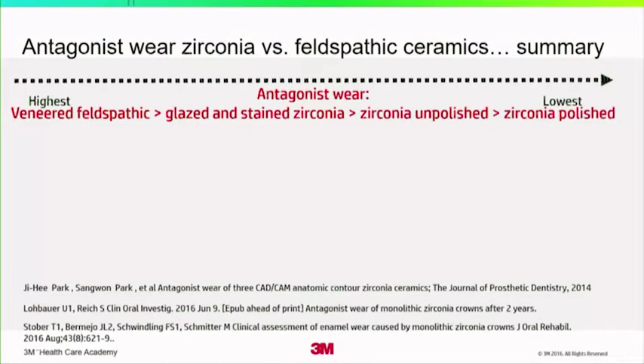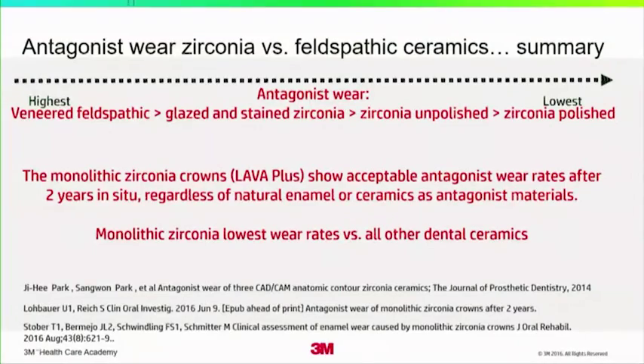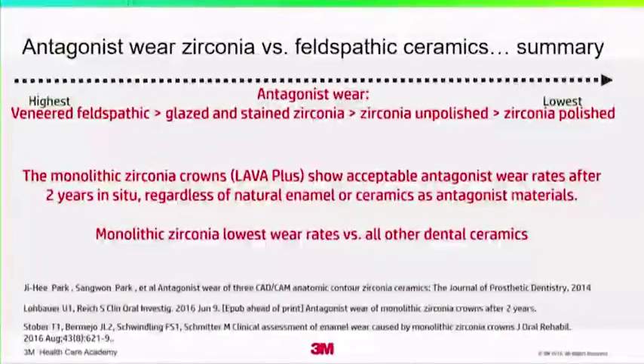So, in summary, what we know about antagonist wear of zirconia versus the feldspathics is that the wear for veneered feldspathics is the highest. Going down the scale, we can conclusively state that polished zirconia is definitely the lowest wearing material that you can put opposite any type of material that you currently use in dentistry. Monolithic zirconia has the lowest wear rates versus all other dental ceramics, and a number of studies have supported this fact. So if you're going to think about how you handle your materials at the chair, this may influence how you want your laboratory technician to deliver this restoration to you.